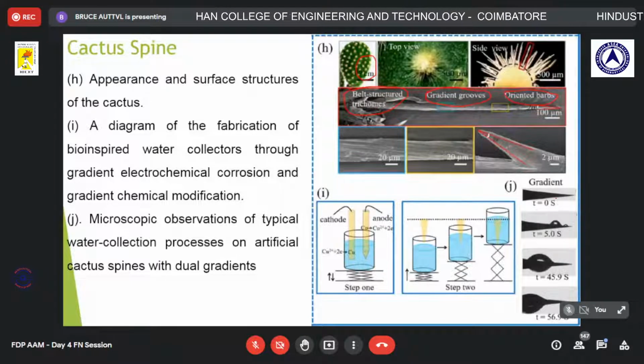Okay, so you just see the gradient here at t equal to 0 seconds. What happens is in this oriented barbs, as I mentioned, some significant roughness is there. So the water droplet comes down here, and here in the gradient grooves, some significant roughness reduction is there. So the surface free energy enables the droplet to move further, and once it reaches the belt structured trichomes, it is collected to nourish the cactus.